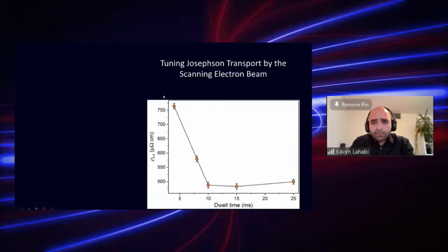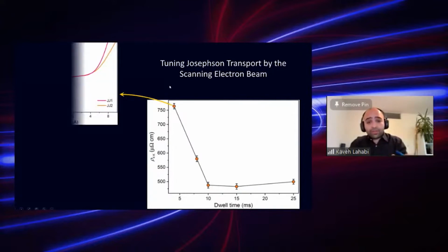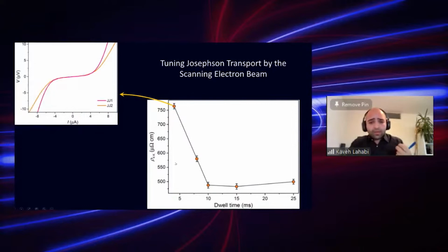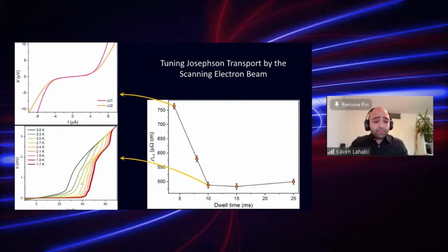What I want to show you, and it's perhaps more interesting, is that we found that by tuning the beam parameters when depositing the weak link, the non-superconducting part, we can actually control the critical current of our junction. If we deposit it with a faster scan, let's say small dwell time, we'll always get a critical current of about 4.5, 5 microamps. But if we do it with a 10 millisecond dwell time while scanning the beam, then we can boost the critical current to somewhere around 40 microamps.